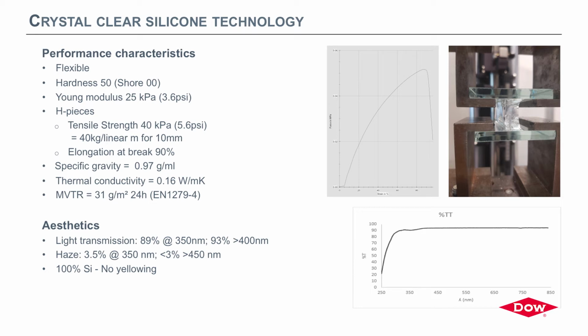So this is really based on extensive testing. So we have performed ETAG testing, as you know, varied aging conditions, and verified that our properties are stable. Now, as we are working with an unfilled system, we see some variety, not due to the aging, but due more to the manufacturing of the H pieces. And so we have set at 40,000 Pascal our tensile strength limit. So this means we can take 40 kilograms of load per linear meter when you have a bond of 10 millimeters. For the moment, that is our typical size. The elongation at break is 85 to 90%. And the specific gravity is less than 1.